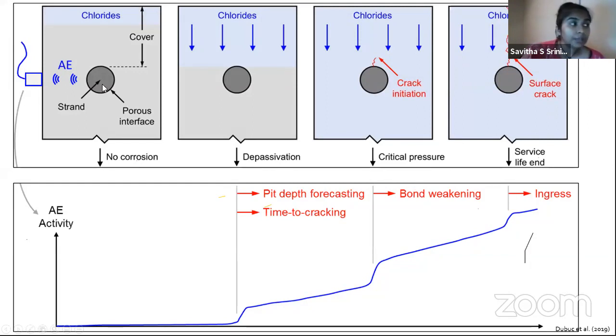So say you have your strand, and once the chlorides start penetrating, you have a crack initiation, followed by the crack extending all the way to the surface. So when we look at the acoustic emission activity, till there's no corrosion, you have very, very little acoustic activity. And once the chlorides start to penetrate and the time to cracking starts, you start seeing small amounts of increase in the acoustic activity. And similarly, as the cracks increase, you have a much higher acoustic emission activity.